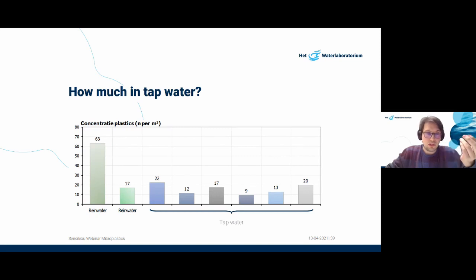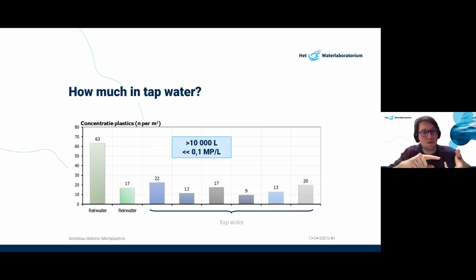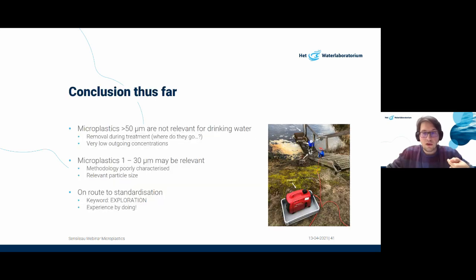So the question then: how much is in tap water? Well, these are the numbers. What they basically mean is that we sampled more than 10,000 liters of water coming from your tap, and we found a lot less than 0.1 microplastic per liter, and that is without correction for any possible blank effects from the lab or from the sieves themselves. So the most likely conclusion we had to draw is that there are no larger microplastics in the tap water. Now, of course, that is the interesting conclusion, regardless of whether you take the blanks into account.